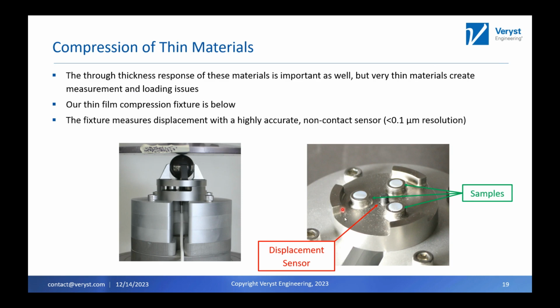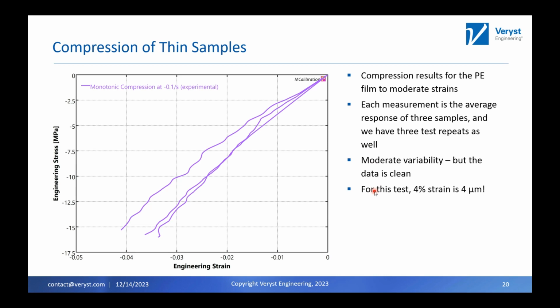So the force is distributed between the 3 of them, and then the displacement is the same for all 3. So each one of these is an average of 3 samples. So this really means that we've tested 9 samples. And you can see that there's a little bit of variability, but not too much noise. There's a little bit of waviness in the stress and the strain, but not a lot.